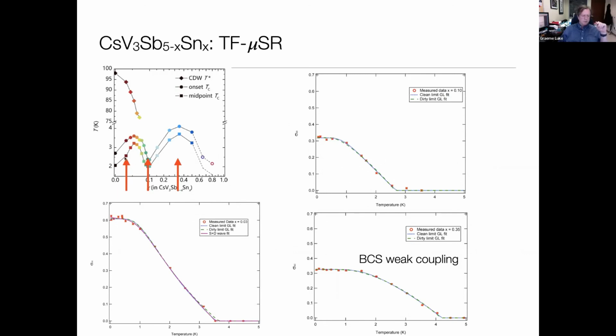One with about 3%, where you've reduced the ordering temperature of the CDW significantly, and you've raised TC up from about 2 Kelvin to closer to 3 Kelvin. So the onset temperature here is about 3 Kelvin. And then we looked at a sample right at the minimum, at a doping of 0.1, with the lowest TC in the series. And then a third sample that was up near the maximum, and we want to look at each one of these.